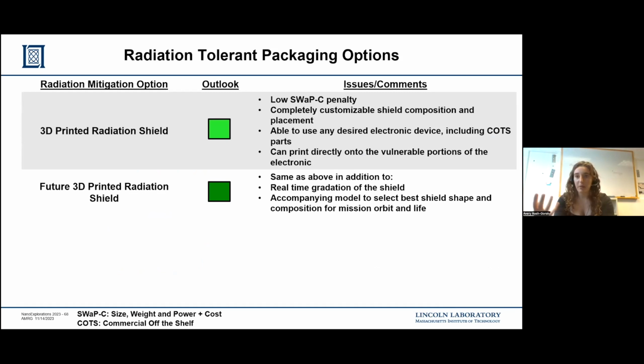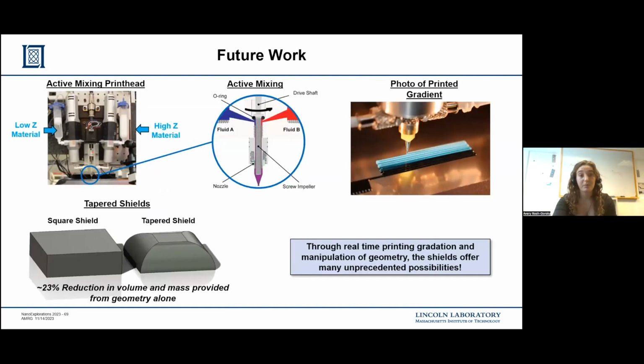So if you remember from our stoplight chart in the beginning, our future work wanted to have the real-time gradation of our shields so we can have that benefit of stacking the shields. And we also wanted an accompanying model to select the best shield shape and composition, including gradation, for mission, orbit, and life. So in order to create a more homogeneous mixture for our gradation, we need to create an active mixing nozzle, which is what you can see in the middle. And this is done with a screw impeller, and you basically apply different pressures to the different inks. So then you can influence the amount of each type of ink actually being printed. If you look at the image, we go from black to cyan, and it's this really nice grading as you go through.